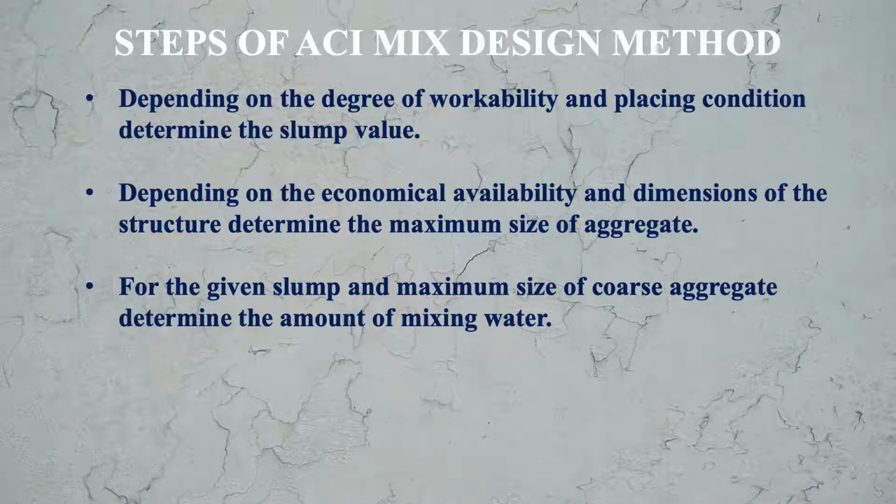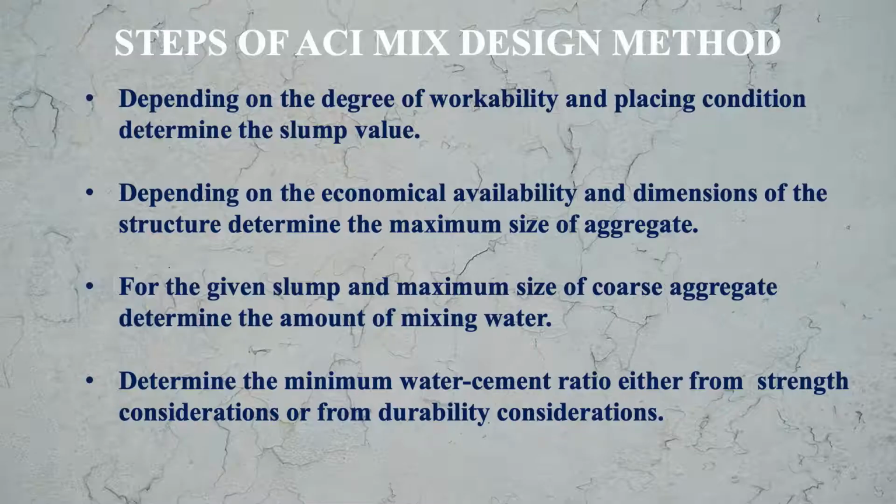If the size of the structure or the structural element is large, then you can go to the larger size of aggregate. Next step is, for the given slump and the maximum size of coarse aggregate, determine the amount of mixing water. That is, how much water is to be mixed to prepare the concrete mix. Then next step is, determine the minimum water cement ratio, either from strength consideration or from durability consideration.